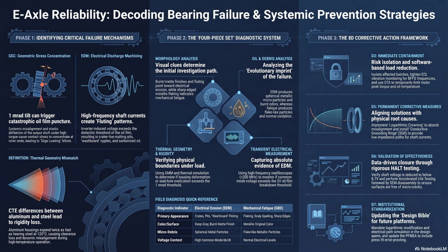Zero. Wait, so the housing is basically cooking in its own heat, expanding outward, and leaving the steel bearing rattling around inside like a loose tooth. It is exactly like a loose tooth, and it gets worse because the housing doesn't expand perfectly into a larger circle. Because of the shape. Right, it has structural ribs, bolts, uneven heat from the inverter. So the perfectly round hole distorts into an oval. Oh, man. So now you have a rigid steel bearing and an asymmetrical expanding oval hole. The constraint keeping it parallel is just gone. The moment torque hits, it's physically shoved out of alignment. We're building a precision instrument inside an oven that's actively changing its own shape.